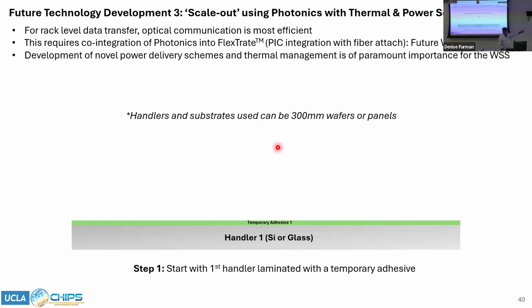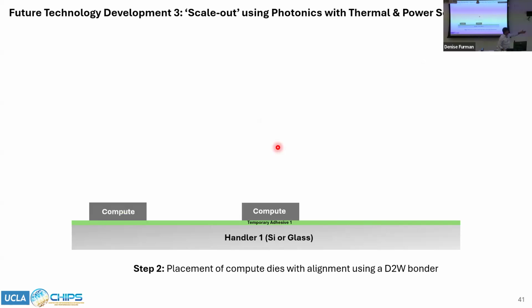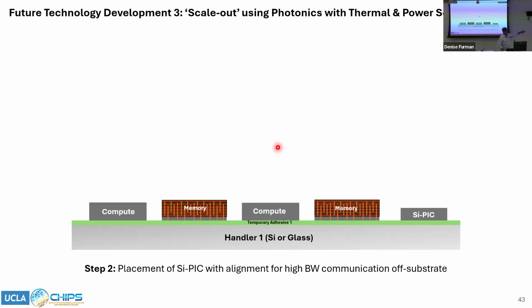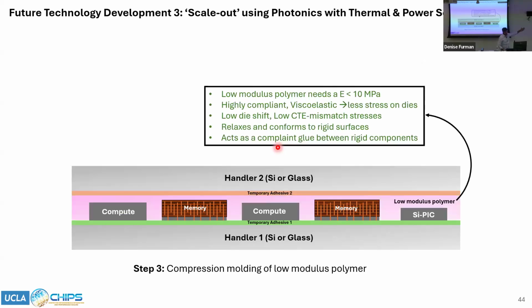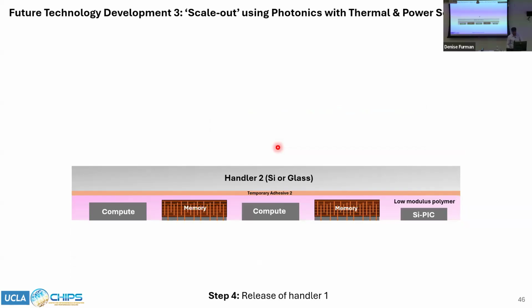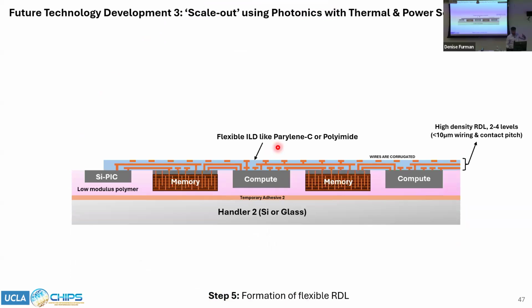So say we start with a handler wafer, 300mm with some thermally releasable tape. We first place the compute dies, the memory die, and the silicon PIC. And then we can compression mold this low Young's modulus polymer. It's very important that the polymer that we use has to be low Young's modulus, less than 10 megapascal, so that it can be compliant and viscoelastic, and also ensure that it has low die shift and CTE mismatch stresses.